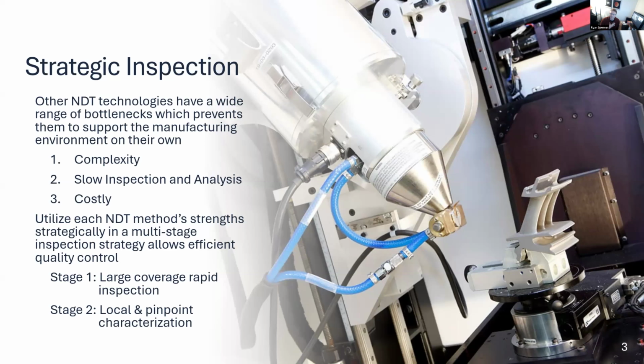So that's where we step in, and we believe there is a multi-stage approach you should take with your inspection methodology. First stage, let's do a large coverage, large field of view, and rapid inspection. See if locations cross a threshold and highlight hot zones in order to do an initial detection. Then you can go into stage 2, either with our technology or traditional technologies, where they provide a localized and high resolution characterization of those defected areas. This brings a balance between having that rapid inspection and detection, and also having those fine details and local inspection.